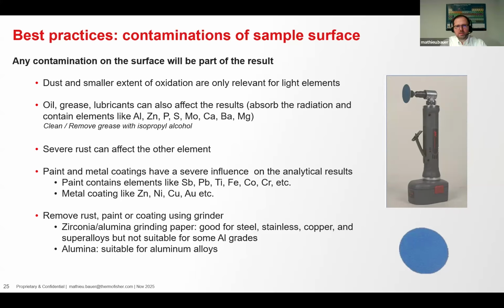There might be one exception, for some aluminum alloys, especially those containing low zirconium, where pure alumina grinding paper can be preferred to avoid false positives of zirconium and misidentification, for example, of 7050 grade, which contains a low level of zirconium.